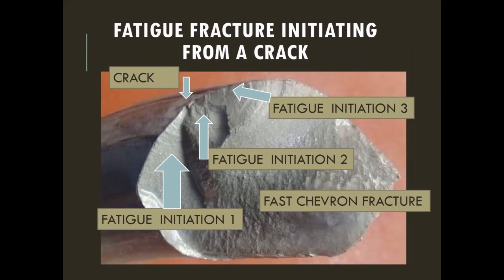This is another case of a fatigue crack propagating in a spring from a small unnoticed crack. From that one crack point there are three fatigue crack initiations: initiation 1, initiation 2, and initiation 3. Initiations 2 and 3 meet in the form of a ridge, and initiations 1 and 2 form a ratchet. The rest of the fracture is a chevron fracture.